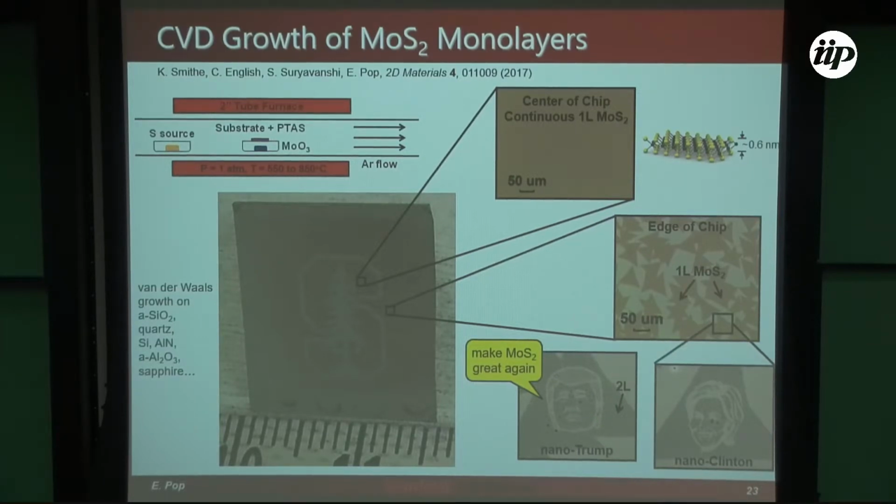And so those dots actually really worried me when I first saw these pictures. And I realized that actually our growths are not as uniform as I wanted them to be. Those are bilayer regions, by the way. So mostly we get 90% monolayers, but we get 10% bilayers. And we don't have extremely good control with these CVD growths.